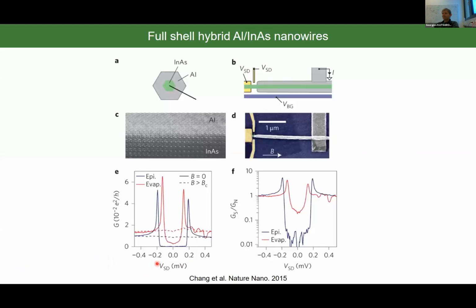We believe that a solution to this problem, a way to distinguish Majoranas from Andreev bound states, comes from a slightly different platform: full shell hybrid aluminum indium arsenide nanowires. These are nanowires, in the particular case indium arsenide nanowires, which are fully covered by an aluminum shell. And obviously this needs to be done in situ. So these wires have been grown by Peter Krogstrup by in situ growth of an aluminum shell, which means that the shell is epitaxially grown. And in this figure, you can already see that the aluminum induces a very hard gap into the semiconductor.